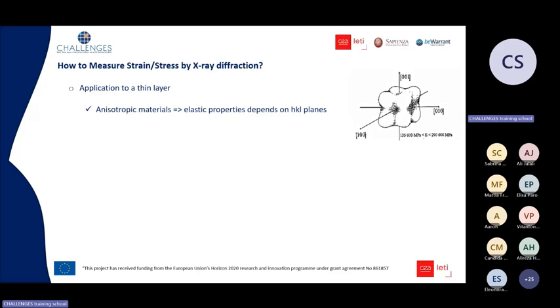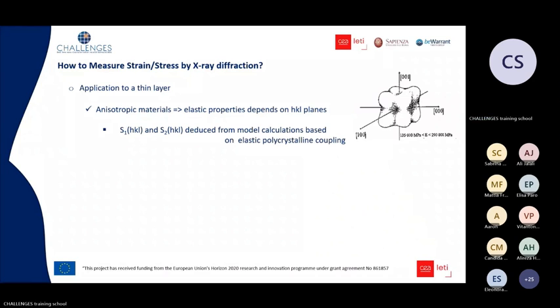So maybe one comment about the S1 and S2, so the X-ray elastic constants. The problem is that for anisotropic material, the elastic properties depend on the HKL planes. So if you push on the 001 direction or on the 111 direction, you will not have the same strain result. So it means that the elastic constant we have to use should depend on the HKL and can be calculated through different models. I will not detail here.